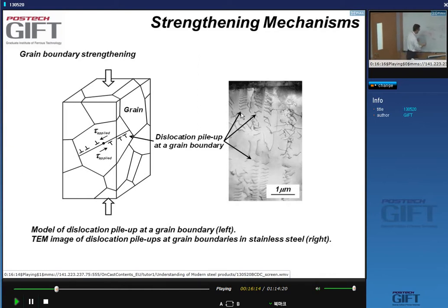So one of the things you see if you look, for instance, in the microscope, is that the more dislocations you have, the further apart they are. You can see it very nicely here: the dislocations are closely spaced at the boundary and then further and further apart. It's an expression of the fact that you built up a stress here at the grain boundary, which pushes back the dislocations that are arriving at the grain boundary. So you get stress concentrations at the grain boundaries.